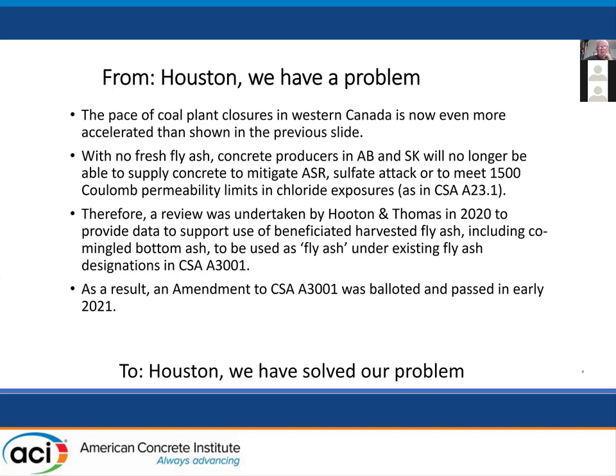And so we had a problem because in Western Canada, the only SCM they had available was fly ash. And they have alkali aggregate problems. They've got severe sulfate exposure problems. And of course, with de-icer salts, they've got chloride exposure problems. Without fly ash, they can't make concrete that meets the Canadian standard for concretes in that environment. They couldn't mitigate ASR, they couldn't mitigate sulfate attack, and they wouldn't meet the Coulomb limits we have in our standard for chloride attack.